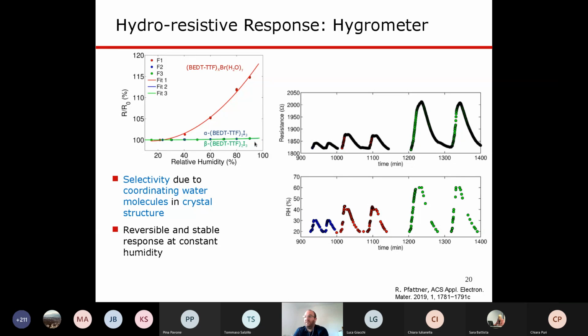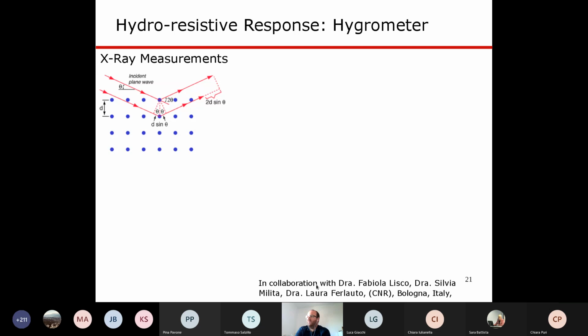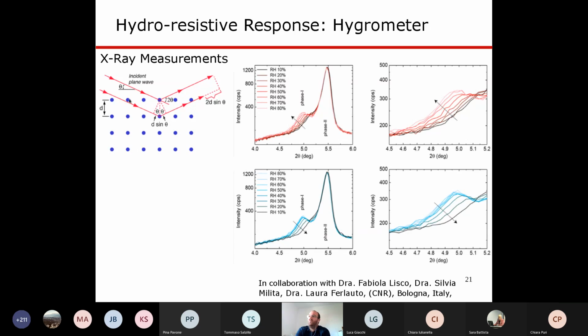Now, okay, the humidity sensor seems to work, but we wanted to figure out and understand why or how it is working. So we reached out to a very nice group, specialists in XRD at the CNR in Bologna, and they were actually very good at measuring, as I mentioned before, this distance between the molecules. And what we decided was that we wanted to measure this distance between the molecules at different humidity. So what we did is we started to record spectra of these films and exposed them to different humidity levels. We started at very dry conditions at 10% and then went all the way up to 80%. And then from 80%, we went back to 10% to dry again.